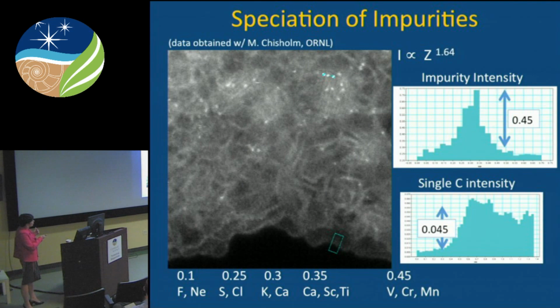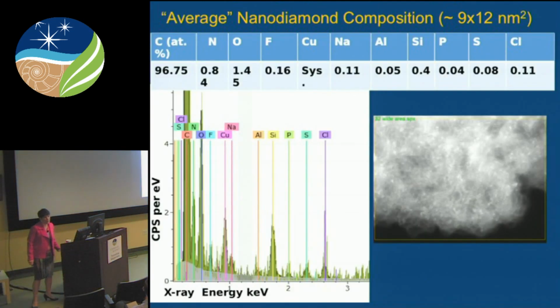All right, so if we wanted to know what those individual impurity atoms are, because those are going to help us distinguish the origins of the individual atoms, we could use the quantitative image contrast. So HAADF, high angle annular dark field images, are in fact quantitatively dependent on average atomic number. So we can take a line profile off the edge into the vacuum into single sheet region carbon and see that 0.045 in intensity corresponds to a single sheet of carbon, and then go measure an individual impurity atom and discover this one's 0.45, an order of magnitude higher, and that's going to translate to an atom of this, so chromium plus or minus Z of 1 or so.